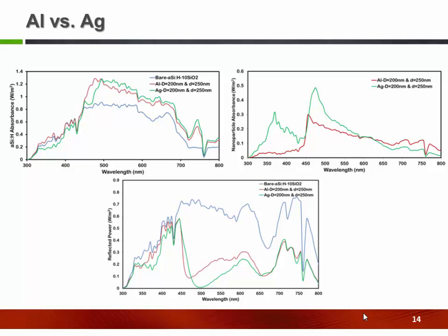But the problem is that silver at the same time has a higher parasitic absorption rate at different wavelengths with respect to aluminum. That's because the parasitic absorption of aluminum and silver is different. The other thing is the reflectivity, where we see that for aluminum the reflectivity is a little higher for some specific wavelengths, so we may want to investigate the parameters.